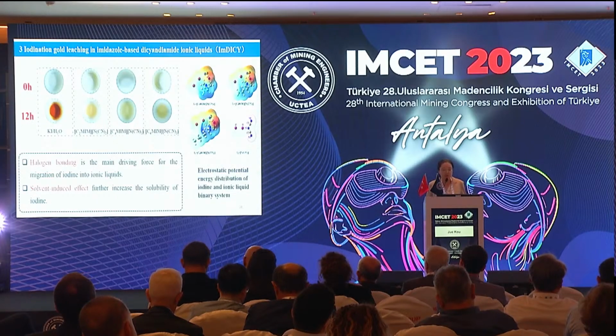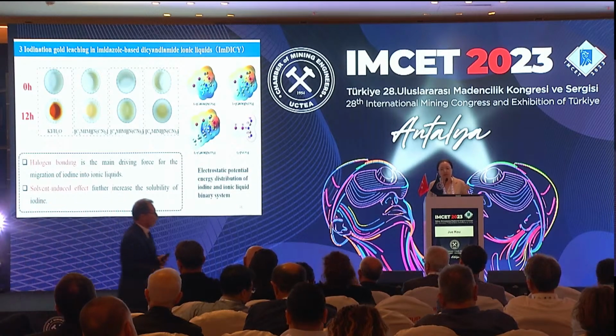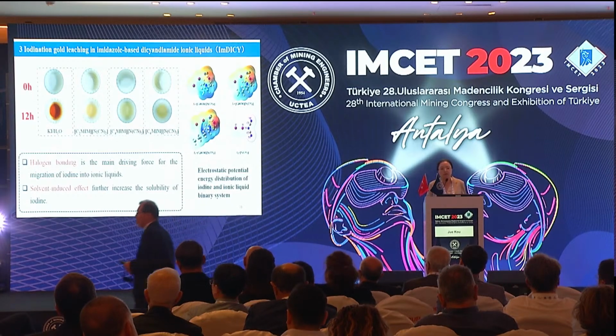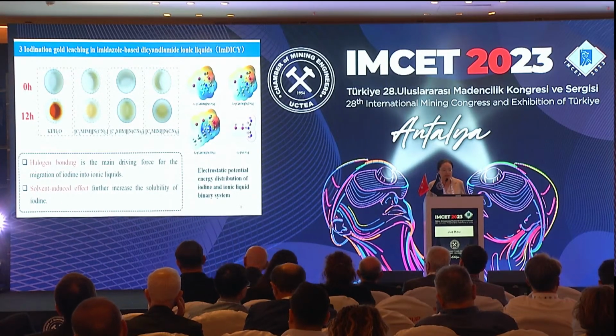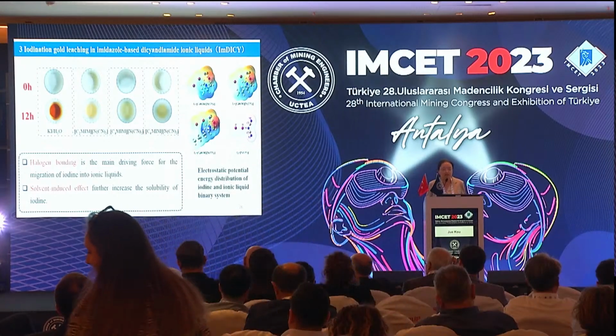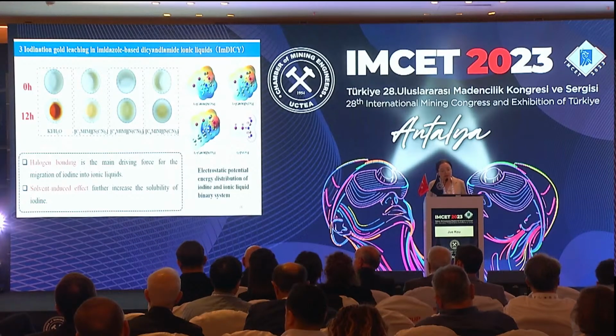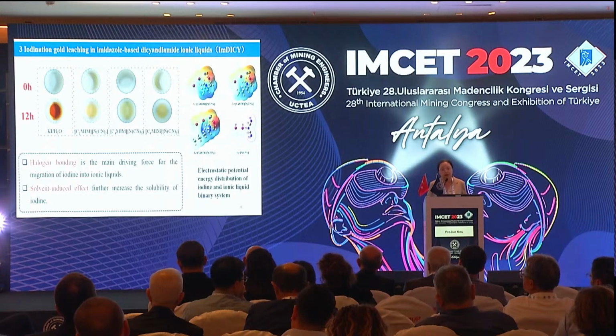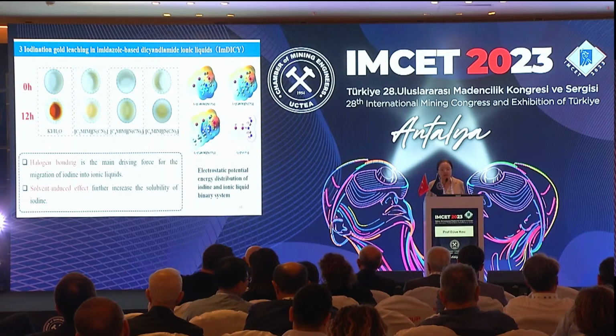This figure shows us how stable the iodine is in the ionic liquid. The first row shows the caps of the containers at the very beginning. All these caps are white with no color on them. After 12 hours, we can see in the water solution, the cap of the container turned dark red, which tells us that it might cause the loss of the iodine. The other three caps are the ionic liquid solvent, and we can see the color is very light and almost no iodine evaporated in the ionic liquid.